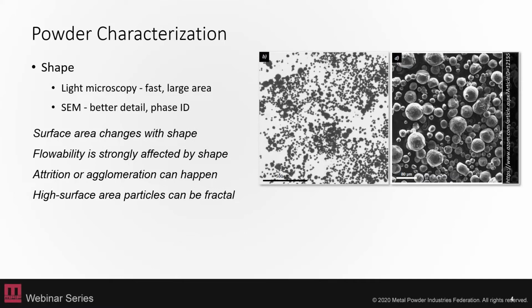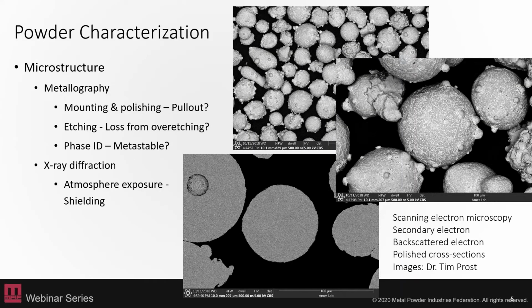When you're looking at your powders, your microstructure is also critical. You can use standard metallography and do mounting and polishing of those powders, like in the center image. Those are powder cross sections in an epoxy mount. But with mounting and polishing, are you getting pull out? Are you getting some loss by over etching your powder particles maybe? Also, your phase ID might not be consistent between powder batches because of your particle size distribution.